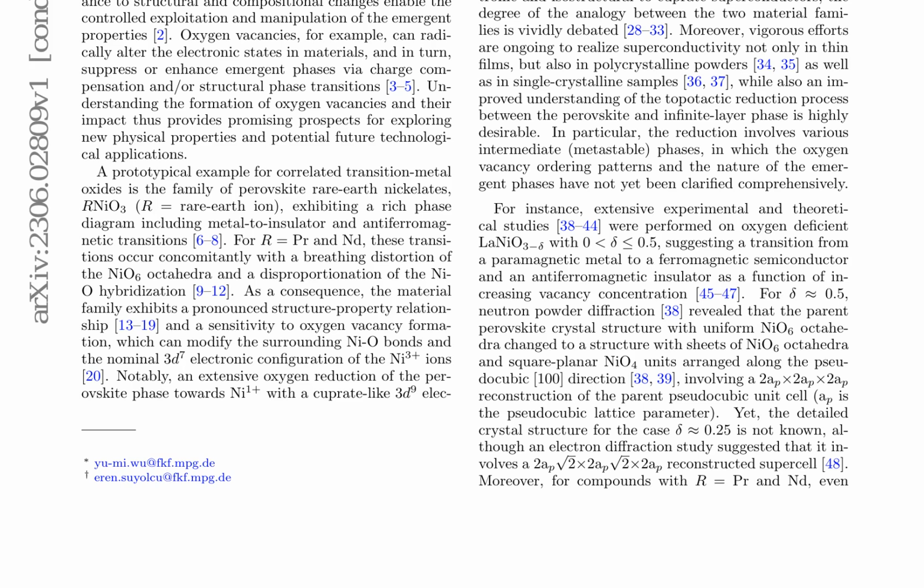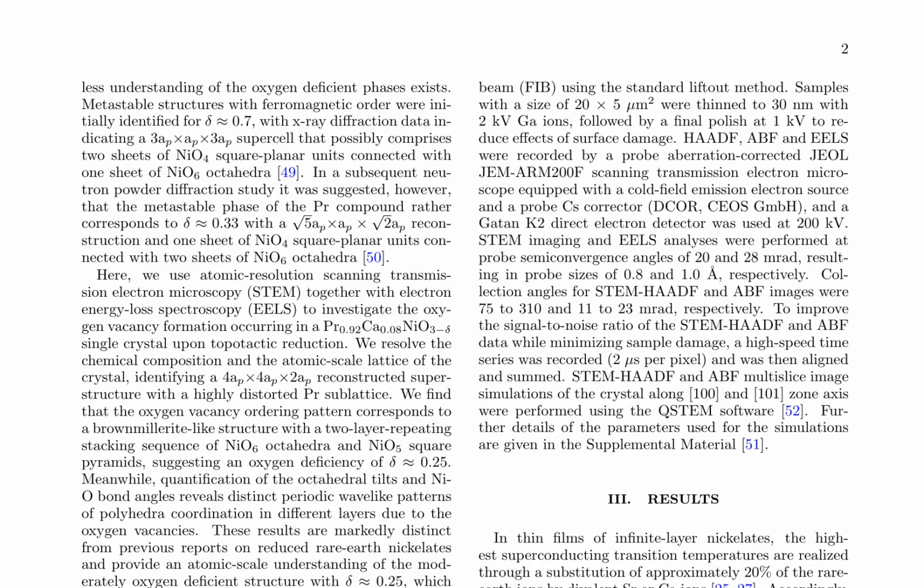the supplemental material. The authors also used atomic resolution scanning transmission electron microscopy, STEM, and electron energy loss spectroscopy, EELS, to investigate the oxygen vacancy formation in the sample. They resolved the chemical composition and atomic scale lattice of the crystal, identifying a brownmillerite-like ordering pattern of the vacancies. The STEM HAADF and ABF data were recorded at probe semi-convergence angles of 20 and 28 mrad, respectively, and collection angles for STEM HAADF and ABF images were 75 to 310 and 11 to 23 mrad, respectively.